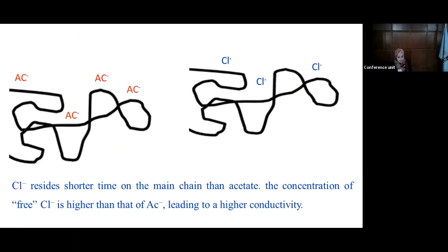How could we interpret that? Actually, we put an interpretation here. If we imagine the chain of chitosan as a linear chain, or simply a linear polysaccharide, but I draw it as a linear chain, an acetate group is moving around like this, and on the other side, chlorine ions are moving around. Acetate groups interact with the chain and reside more time on the chain. And chlorine ions, on the other side, reside on the chain for a short time. This means it moves all the time, meaning it carries current.